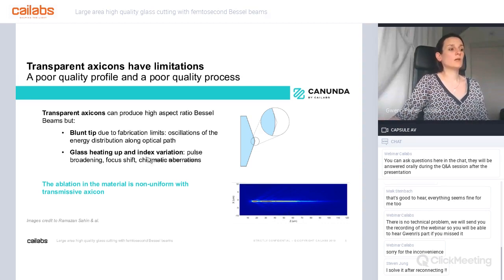The other drawback is that we are using femtosecond lasers. Because they are femtosecond, they have to have a broad spectrum. So broad spectrum doesn't like glass. When you go through glass, all wavelengths are seeing a different index. So you cannot actually keep the pulse duration with a transmissive AXICON. Then if the AXICON heats up, because you are actually sending quite a lot of energy inside it, well, the index will change, and then the different wavelengths will again see another glass index.